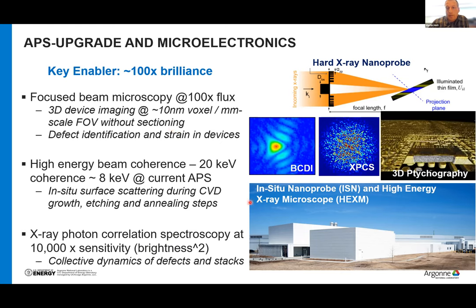Okay, and there are, of course, entirely new beamlines being built on these principles that will be available for use as they come up. This high energy beam coherence, as a few speakers were alluding to, is very different in that a coherent experiment that could tolerate, for example, thin silicon nitride windows can now tolerate thin stainless steel windows, right? I mean, this is entirely different types of chemistry and aggressive environments. Our focused beam microscopy, which is getting down now to 100 times flux, can approach the single defect limit in terms of optical luminescence from these very bright emitters, which we can use as registration for 3D ptychography as well.